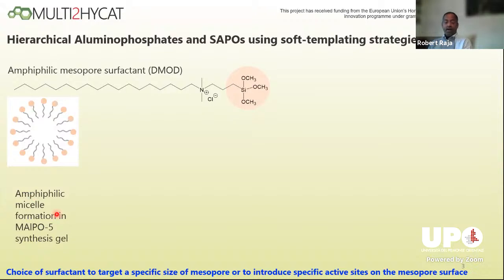It's a zeotype. And as part of the synthetic process, you keep the same process which you use to make the microporous material, but you introduce this surfactant during the synthetic procedure, so one can start to create the secondary porosity. This strategy enables one to mimic the catalytic properties of the microporous material with the advantage of having these interconnected mesopores. So one of the fundamental challenges in catalysis really is mass transport. And with the zeolites, which Silvia talked about earlier, one obviously runs into mass transport problems or kinetic and thermodynamic problems when you start to introduce bulky substrate molecules.